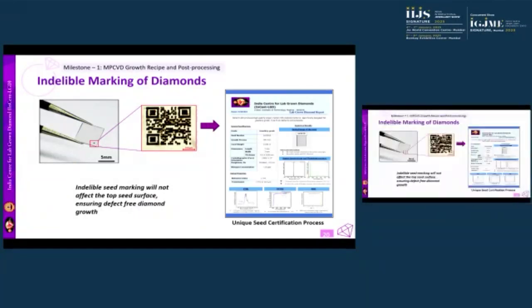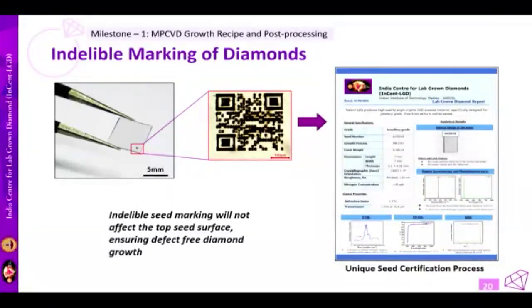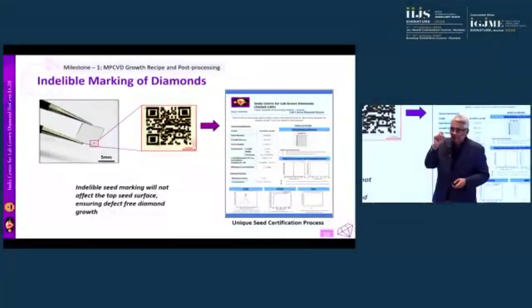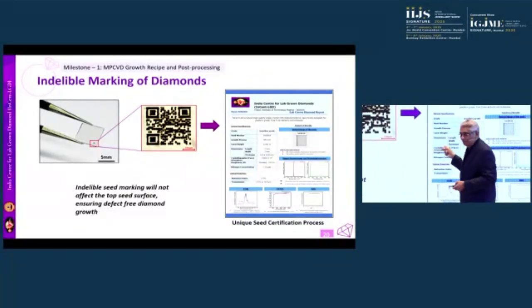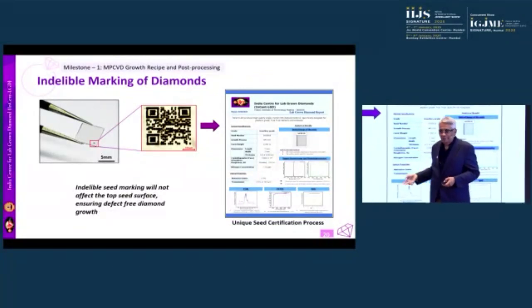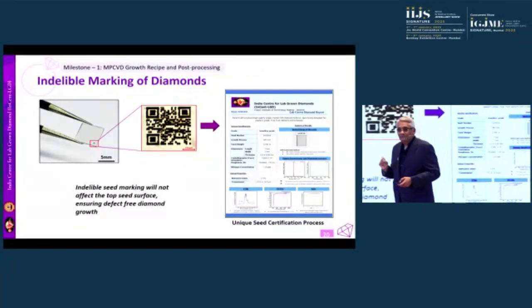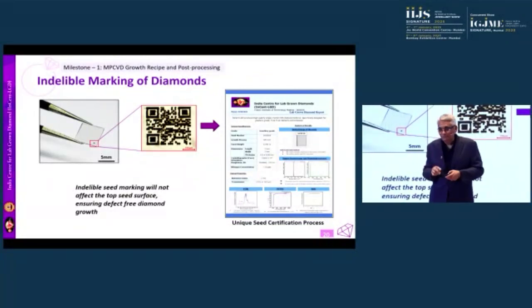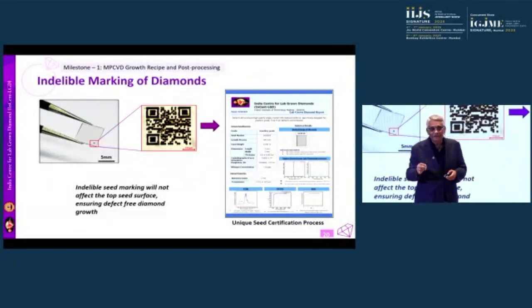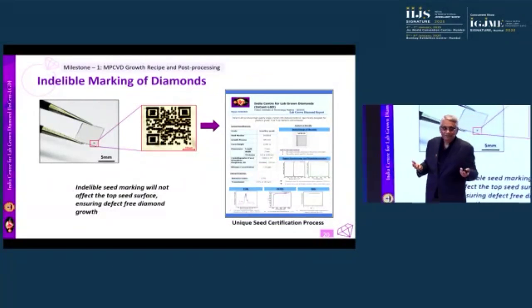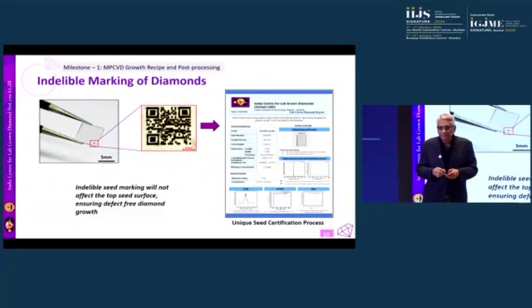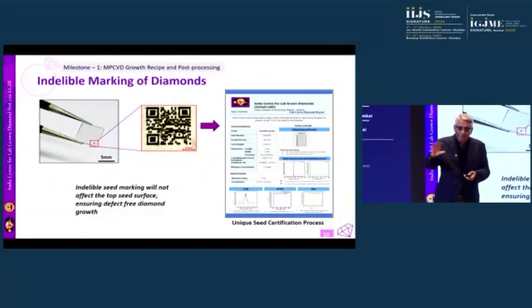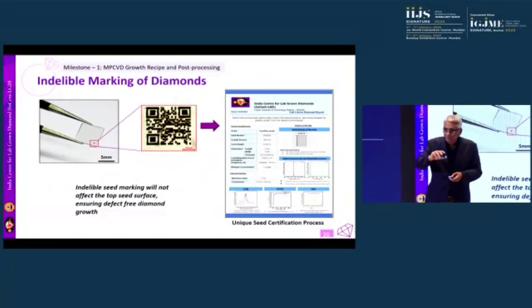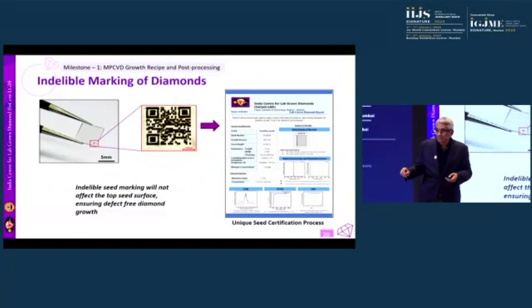See the technology. That one looks like a small speck on your seed, which you can see in our stall. They have a small microscope. What looks like a small speck is actually a barcode. So we can engrave anything, and the diamond structure is not damaged here. That's the most important thing. Diamond remains as diamond. Somebody asks you, what is the guarantee that diamond remains as diamond? We can do tests to prove that this marking doesn't damage the diamond part of it, which is retained.